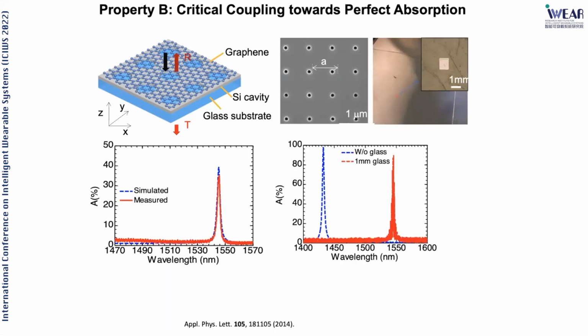What we were able to achieve, without any other complication, is in principle 50% absorption from this monolayer structure, a very compact structure. And experimentally we demonstrated for this particular design about 38%. And if we add a reflector on the backside here, in principle we get 100% absorption, and we experimentally demonstrated close to 90% absorption. So this could potentially be utilized for spectrally dependent detectors or high performance detectors, if we care about the signal to noise ratio, if we care about really only single wavelengths, or sometimes you may want to tune the wavelengths. So those can be considered an interesting detector scheme, based on this principle here.